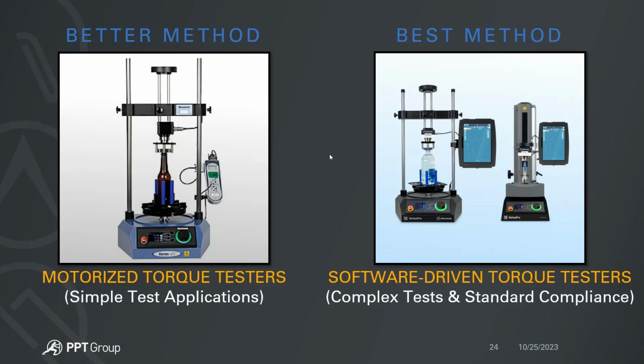Where you can set the speed of the test, run at 2 revolutions per minute, run at 5 revolutions per minute, run at 20 revolutions per minute. Again, the key here is trying to simulate what humans do if they grab the bottle of jam and they wanted to uncap it, and then run to a known angle. 40 degrees, 30 degrees, 360 degrees to keep it uniform. And then we'll measure whatever the torque resistance is. First, we'll get that initial torque that it takes to break the seal or the tamper evident bands, and then the running torque or the average torque that it takes to actually uncap the cap or the container lid from the container.